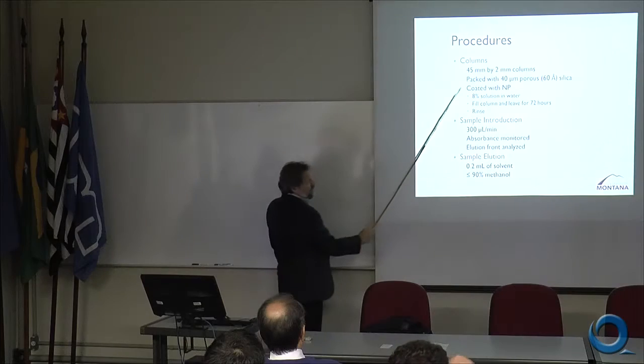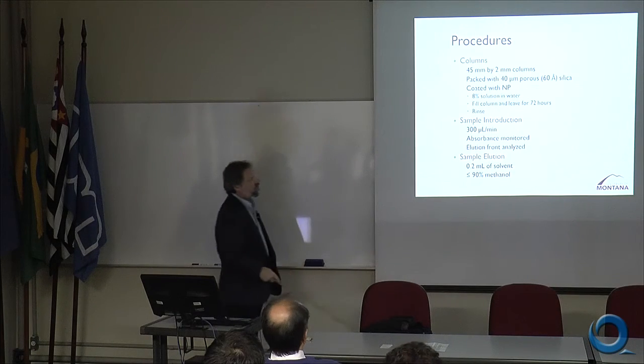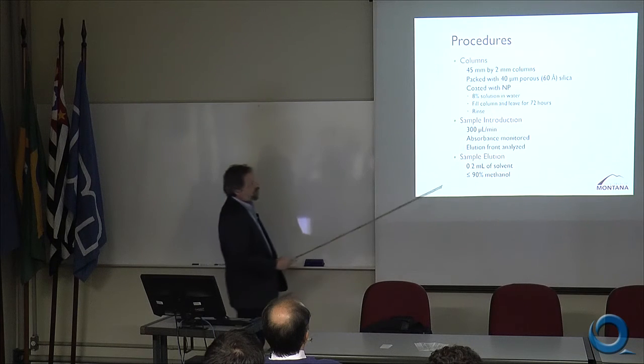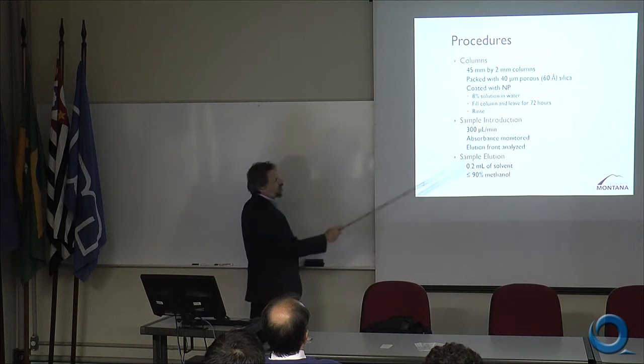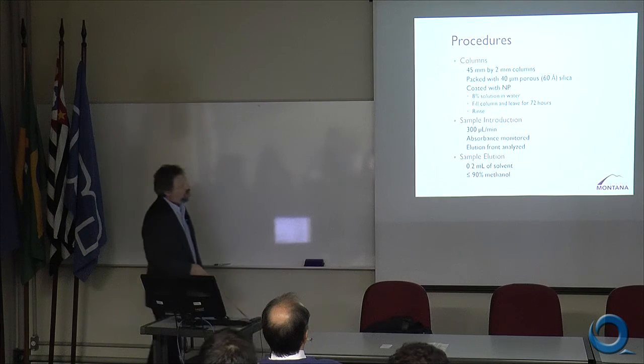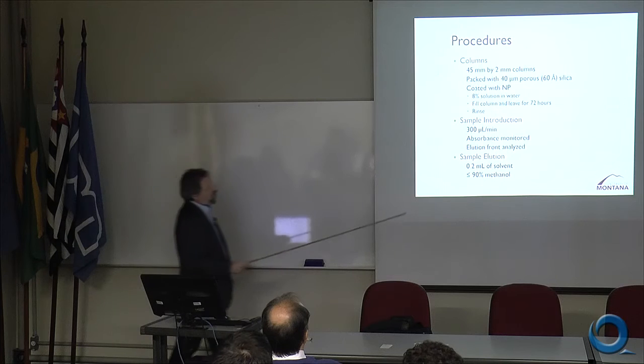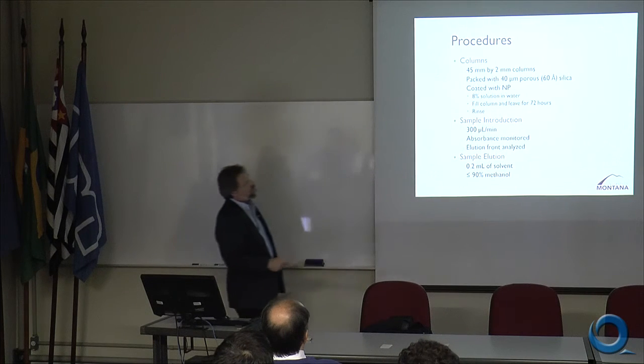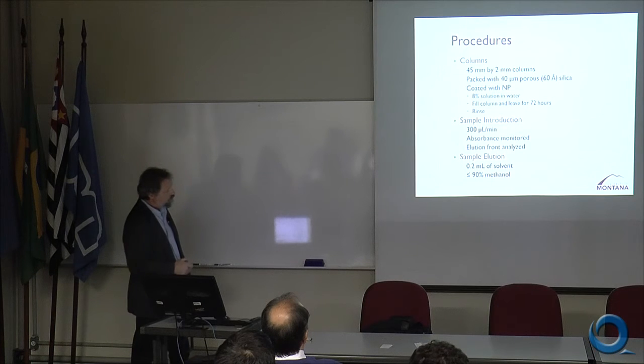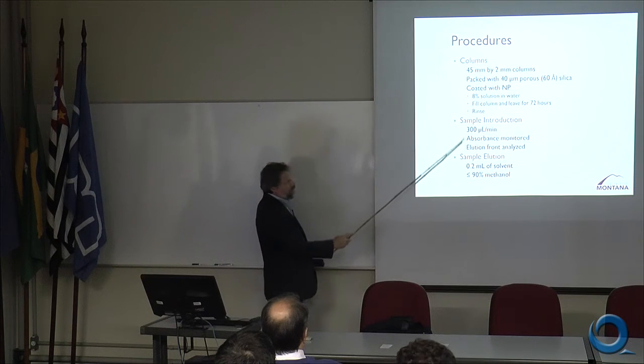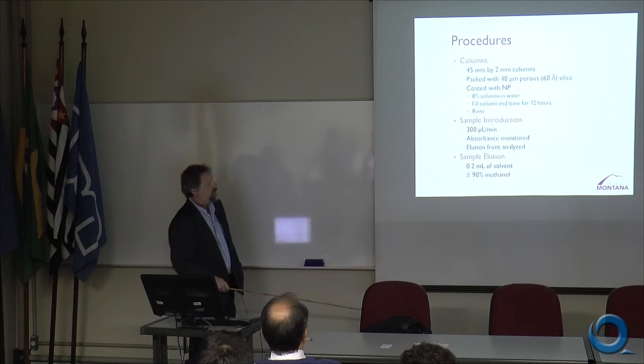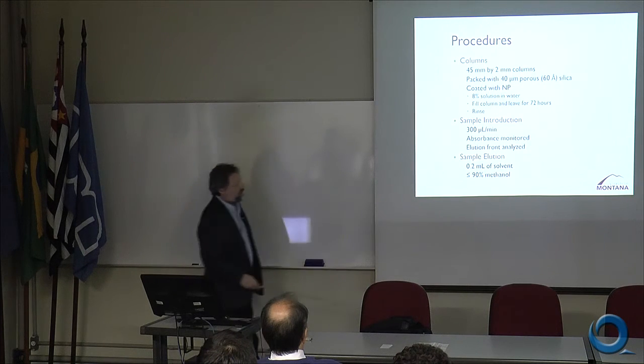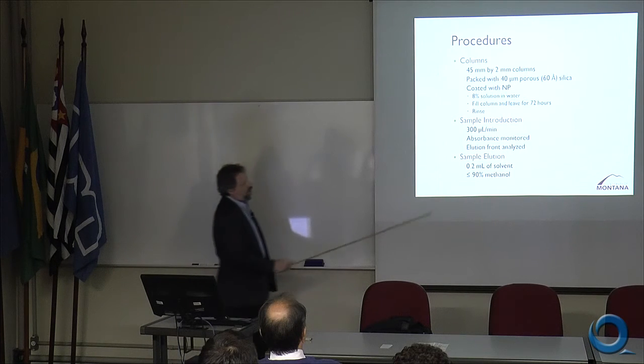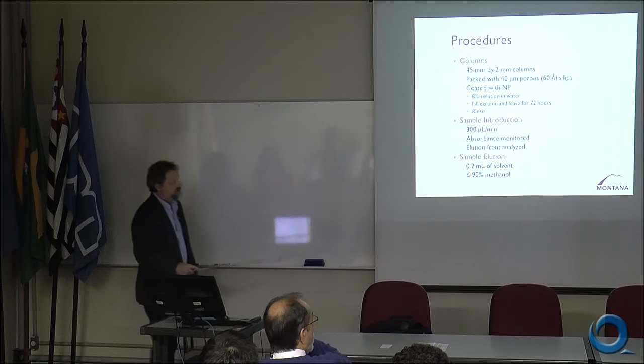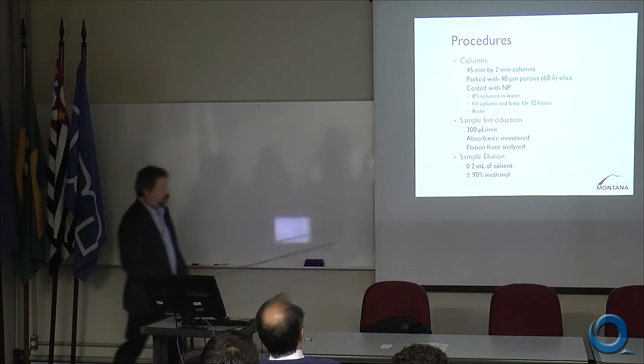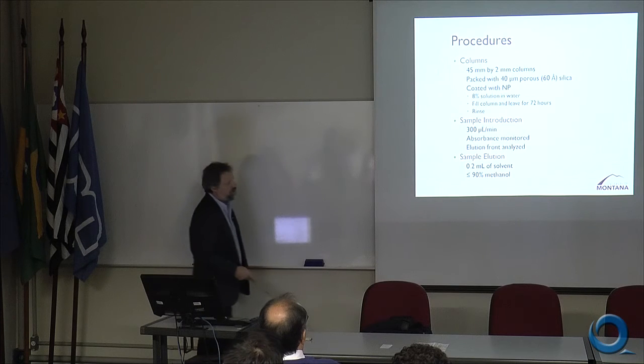We coated these particles with the nanoparticles. We used an 8% solution of the nanoparticles when we could to fill the column. We leave that for 72 hours, which turns out to be from Friday afternoon to Monday. And then we would rinse the nanoparticles out, and we would move on to start doing some sample introduction. Samples were introduced at 300 microliters per minute. We monitored the absorbance and analyzed the elution fronts that we observed, and we would elute the samples from those analytes that were adsorbed to the column. We could elute them back off with 0.2 milliliters of solvent.